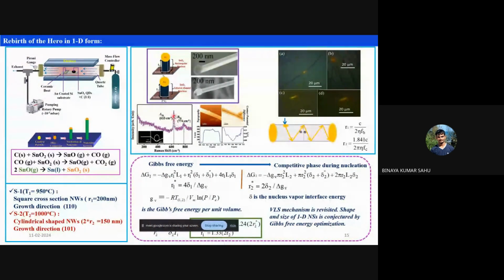Okay. And again, how do we know that this is tin oxide? Basically, we did some Raman spectra. Raman spectra is kind of the fingerprint of the material. So if this particular peak is coming, then you can confirm that my material is formed. So from there we can explain this is tin oxide.